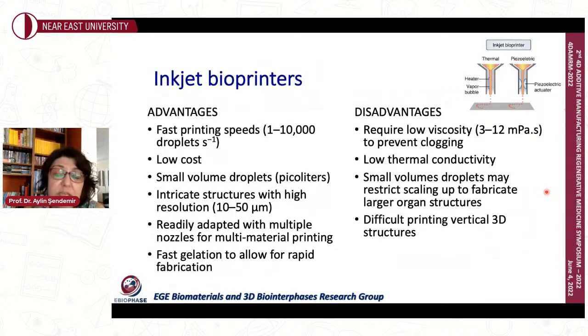With inkjet printers, as I have already said, and even actually Emilia Hoca has already said, they are the fastest. But because they require very low viscosity, like the inkjet printers that we used to have until 15-20 years ago, we use very low viscosity inks. So therefore, the amount of cells that can be incorporated in those inks is limited. So therefore, it's difficult to print 3D vertical structures that are loaded with cells.